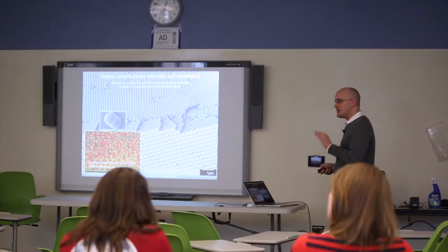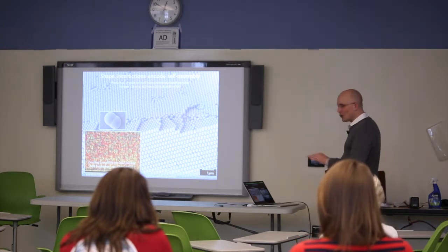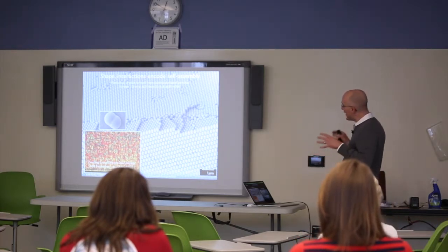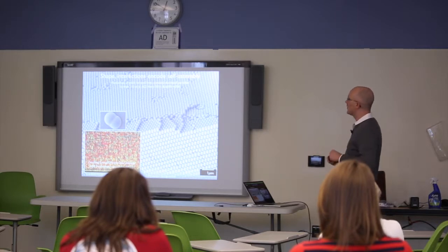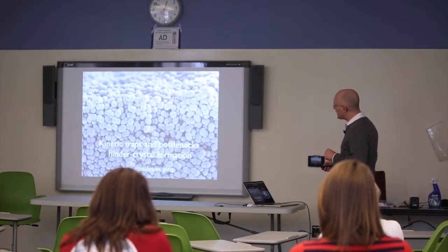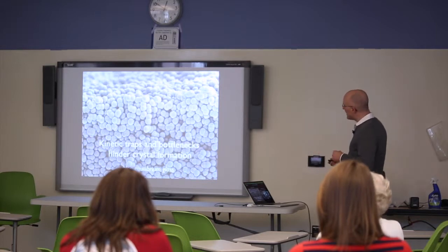The chief scientific hurdle to doing this is the fact that if I take those bricks and I put them in a vessel and I concentrate them up and I expect a colloidal crystal to form, I get something which is known as a glass, something which is disordered and doesn't have that beautiful structure that you saw on the previous slide. And that takes us to the space station experiments.